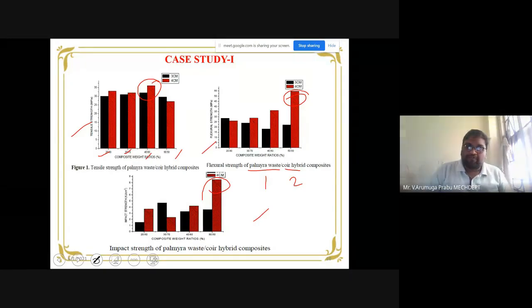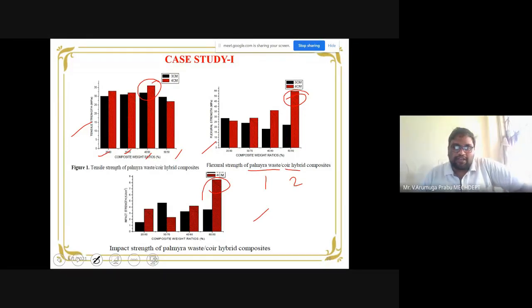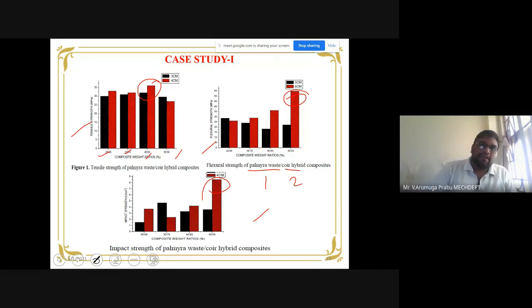So here we changed the fiber length also, 3 centimeter and 4 centimeter, and the higher fiber length possesses the highest strength. That is noticed from all the graphs. That red color is the highest fiber length of 4 centimeter, and compared to 3 centimeter, this 4 centimeter possesses some good results. Okay, so for flexural and impact, 50 is to 50 is the weight percentage which possesses enhancement in results. On the other hand, for tensile strength, the 50-50 is coming as the last one. Only 40 is to 60 has the highest value.